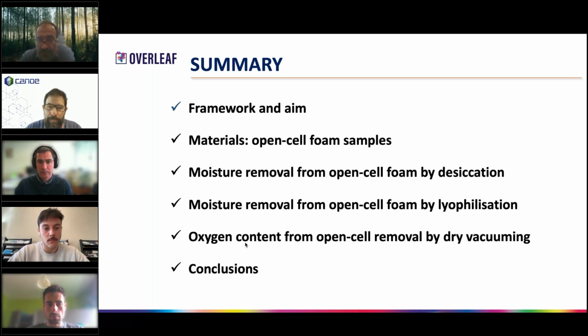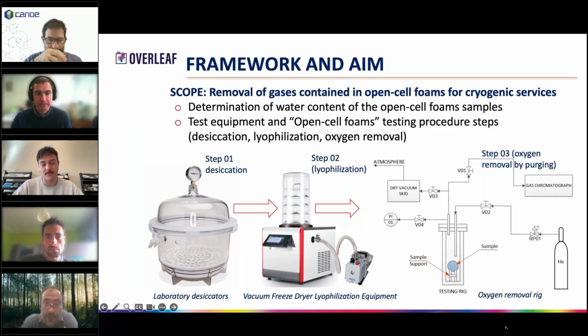As you know, open cell foam is used as a very good insulation material, and due to the specific design of the vessel itself, it was mandatory for us to take not only the moisture out from the system, but also the oxygen. In some specific part of the vessel, hydrogen is in close contact with open cell foam, and the elimination of oxygen is mandatory due to the effect that ice of oxygen has on the liquid hydrogen. We try to take this water and oxygen out from the samples using different approaches.